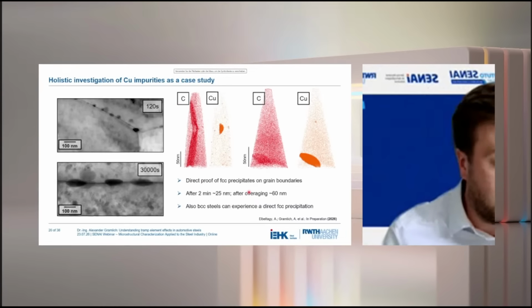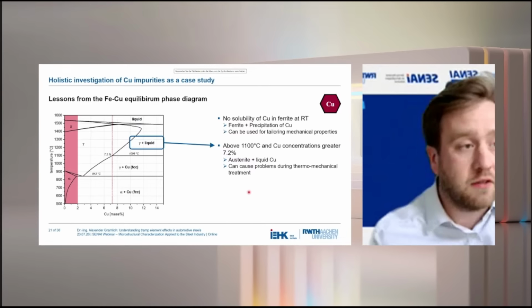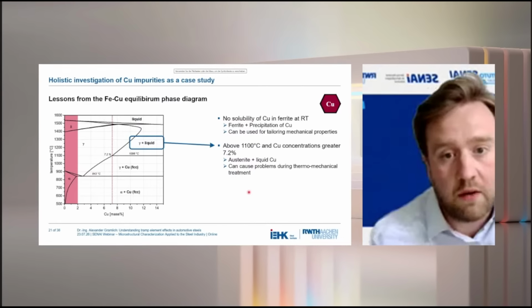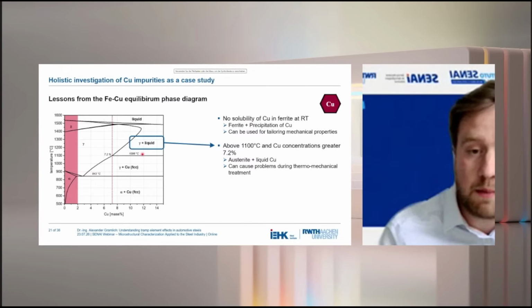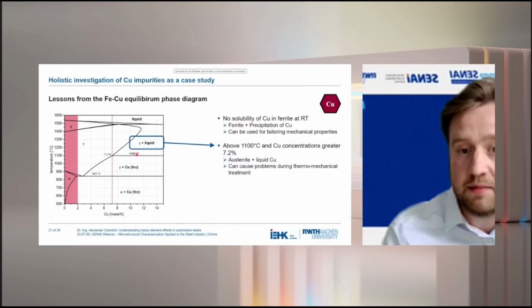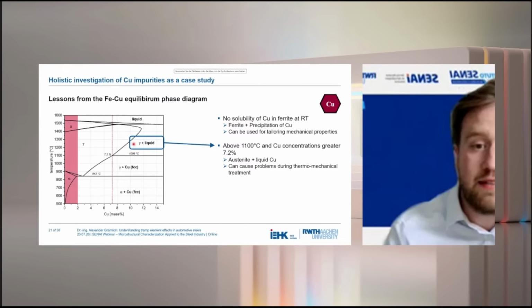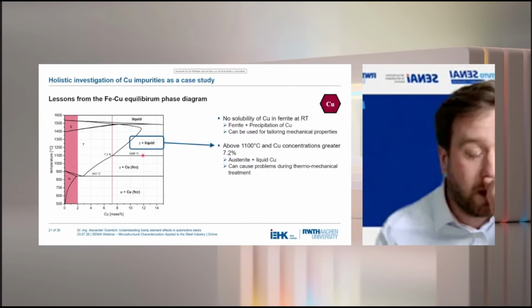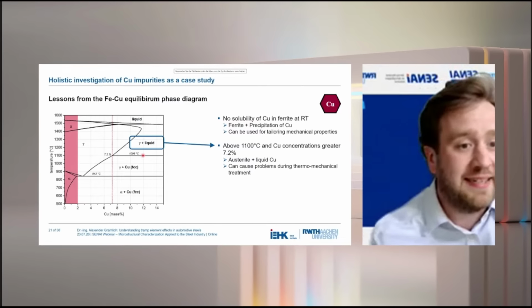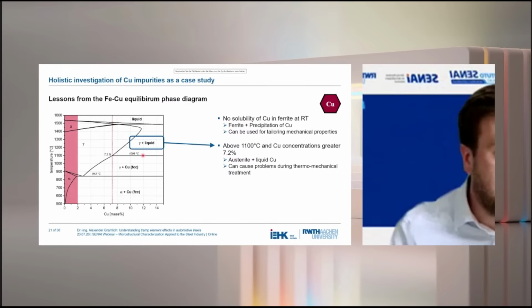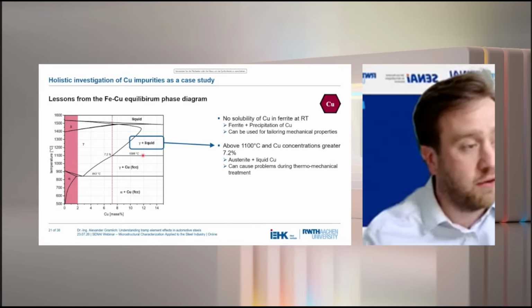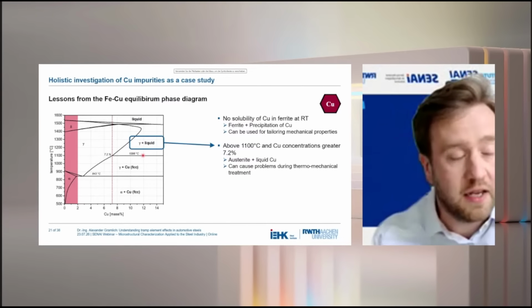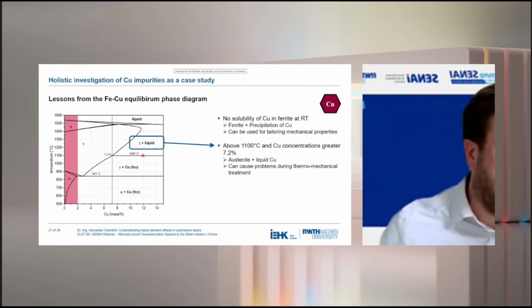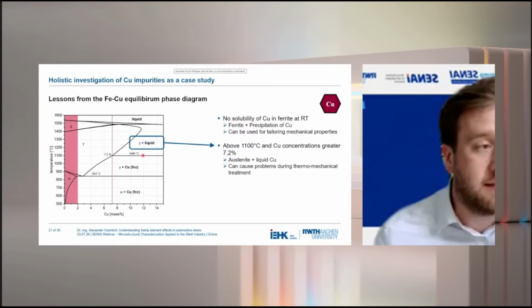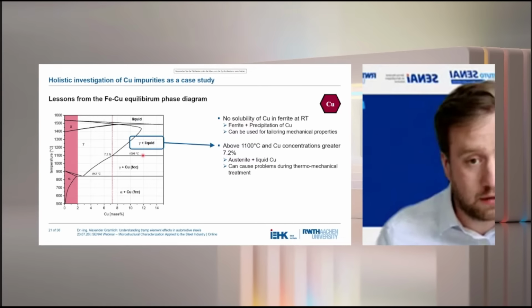So what is the problem with copper? This we can also take from the phase diagram. When we are going to the copper-rich side and to higher temperatures, we can see that already above 1100 degrees, we have austenite and a liquid phase. This means that when you're doing your standard hot rolling, for example, at 1200 degrees, you might get liquid phases, and this will basically lead to catastrophic failure during your hot rolling.